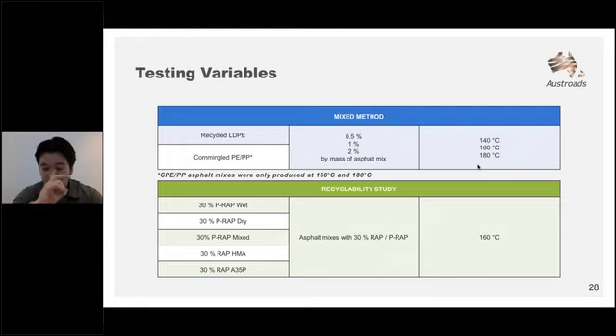And do note that the asphalt mixes containing CPE/PP were only conducted at 160 and 180 degrees, as the plastic itself has a higher melting point than 140. Therefore, it was not considered. And as for the recyclability study, which Dai will get into in a moment, the RAP or PRAP content was fixed at 30% by mass of asphalt mix and produced at one temperature of 160 degrees Celsius. In total, we are looking at approximately 40 asphalt mixes for this study segment.